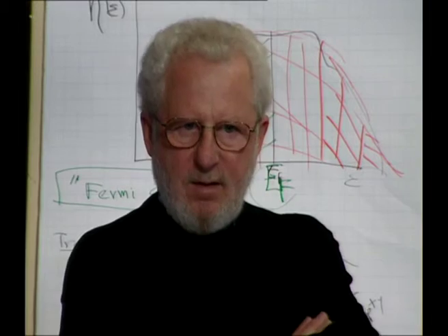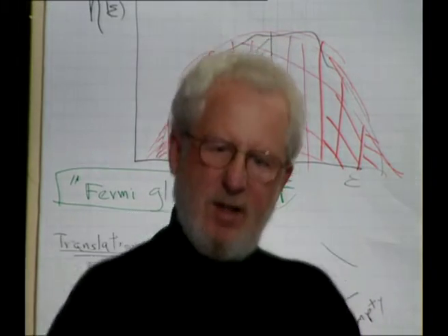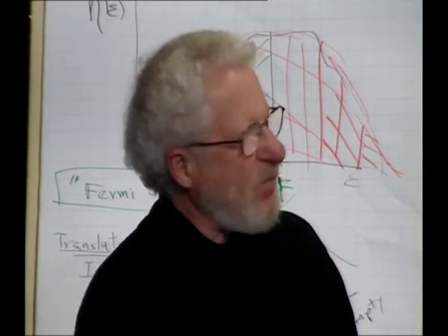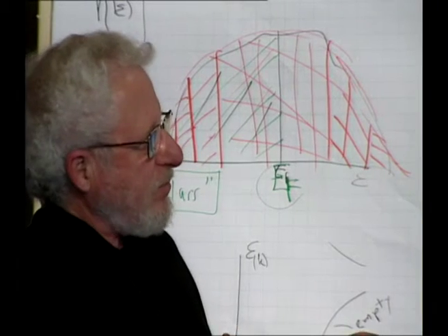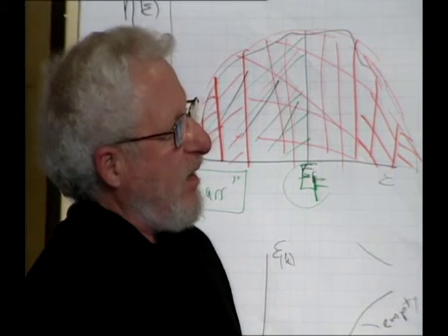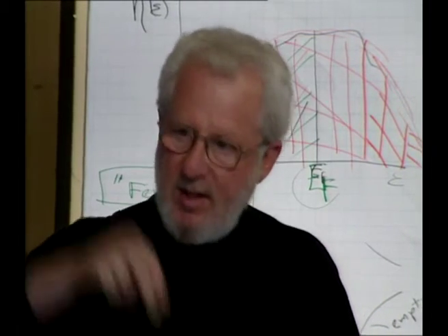In a metal, phonon scattering decreases the conductivity, increases the resistivity, right? Once you go into the insulating regime, you don't have any mean free path. Everything is localized. So now the phonons enable electrons to get out of this state and move to another state.